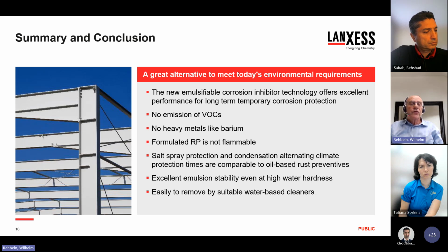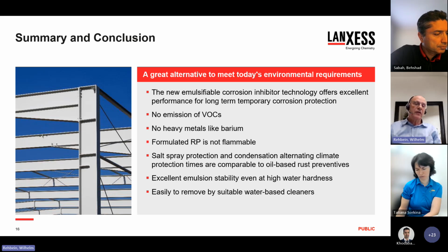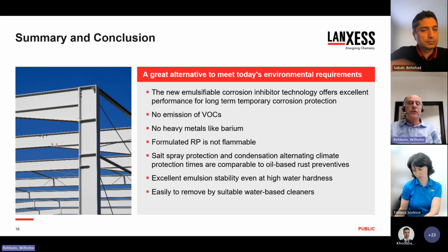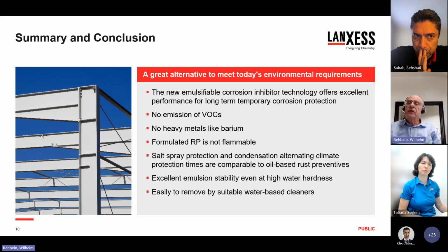And the salt spray protection and the condensation alternating climate protection times are comparable to oil-based rust preventives. We also found that the stability of the prepared emulsion is excellent even at high water hardness. And finally, as I could demonstrate, the protective film of this water-based rust preventive is easy to remove by suitable water-based cleaners.